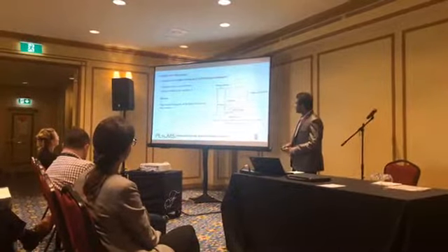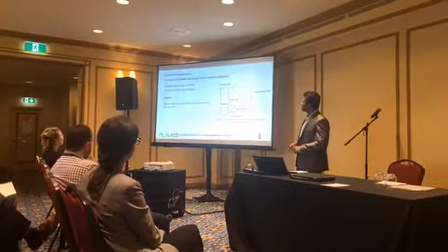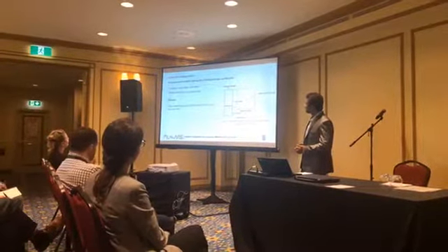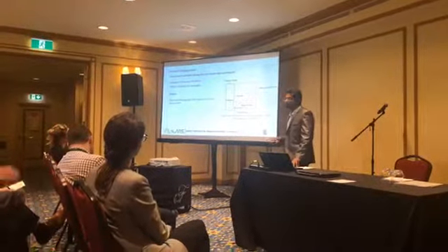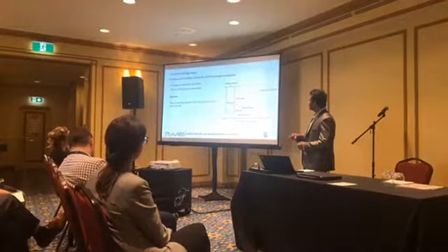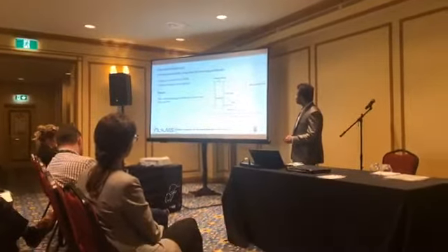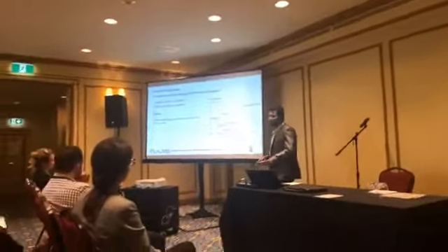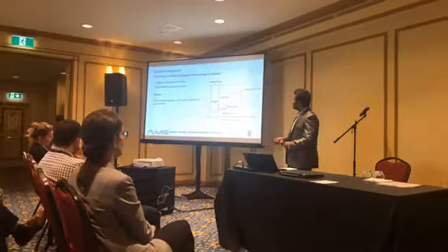We all know that during the 1994 Northridge earthquake, steel moment resisting frames experienced brittle fracture in more than 100 moment resisting frames, and those fractures were mostly concentrated on the bottom portion of the beam column connection. The reason was mostly the low rotational capacity of the weld that we used for designing those connections. Therefore, new generation structures